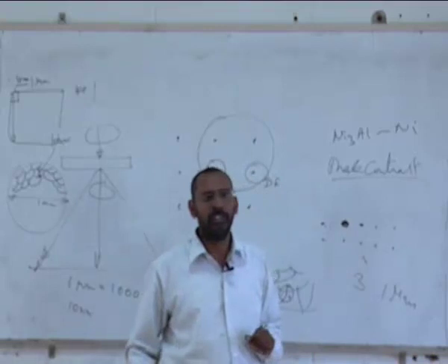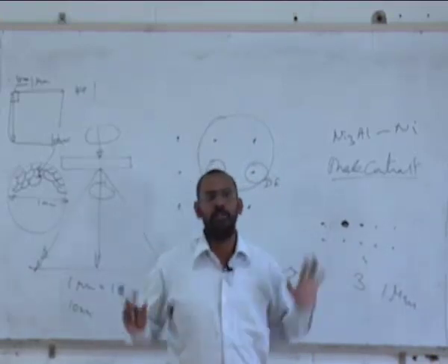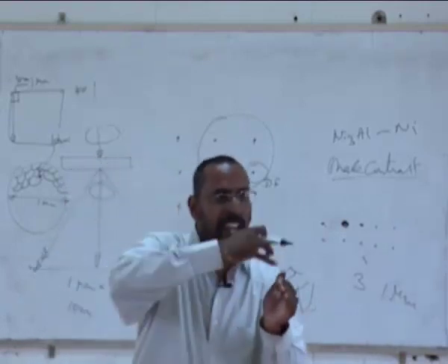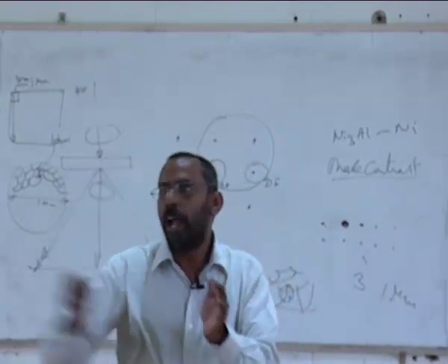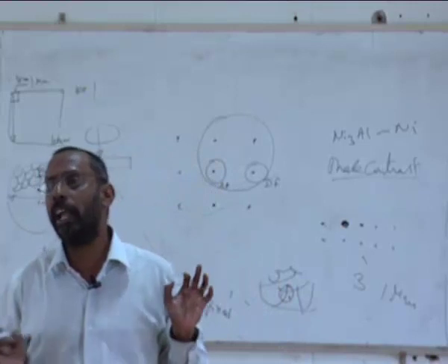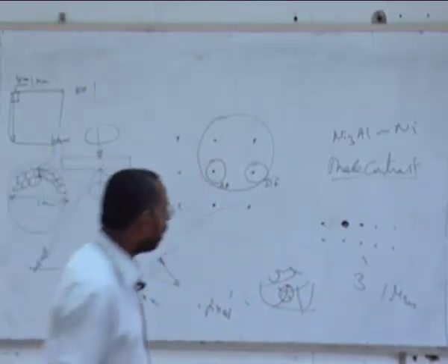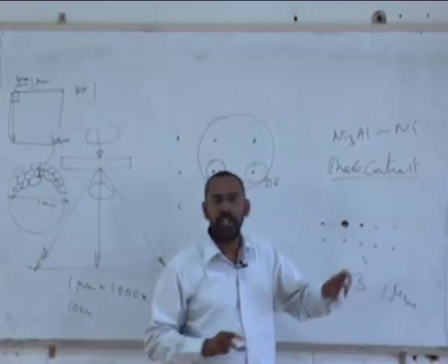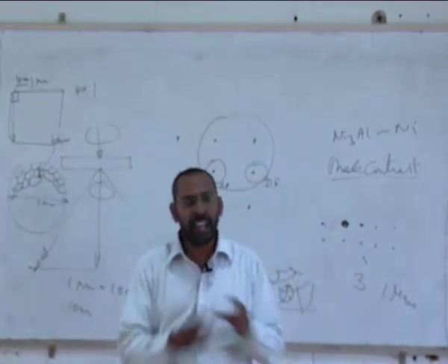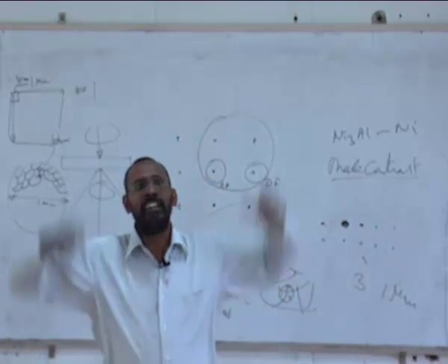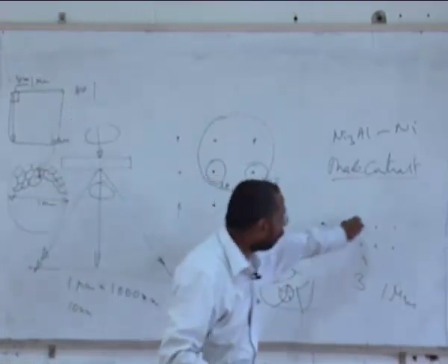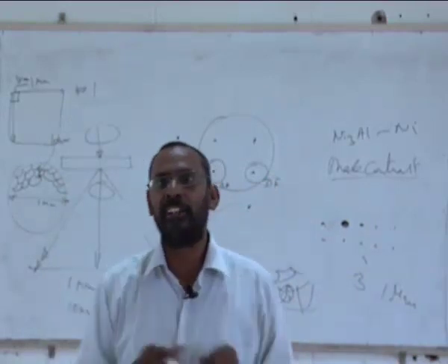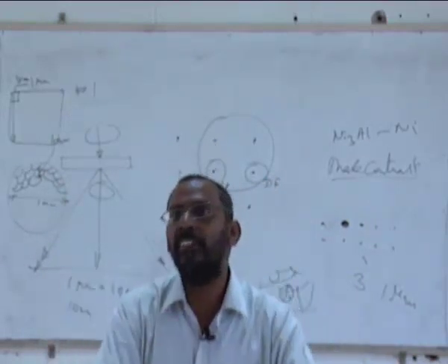Between the two atoms, the electron density is low. If I consider an atom has certain electron density inside it, and between any two atoms, the electron density is low. So when an electron beam falls onto this, the electrons of the atom scatter this electron beam, and as a result, the scattered beam has certain intensity. But between these two atoms, because the electron density is low, there is nothing to scatter this electron beam. As a result, the intensity will be low.